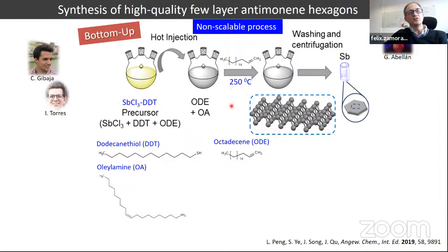The meaning of that is that you get this temperature, 250 degrees, for a short period of time, just a few seconds, and then you observe formation of a dry material, which at the end I'm going to show you corresponds to nano hexagons, few layers of antimony. Okay, if you do this reaction batch by batch, we observe that we have a non-scalable process. The meaning of that is that you are allowed to do the reaction only working with specific volumes of these precursors, so hampering the massive production of material.